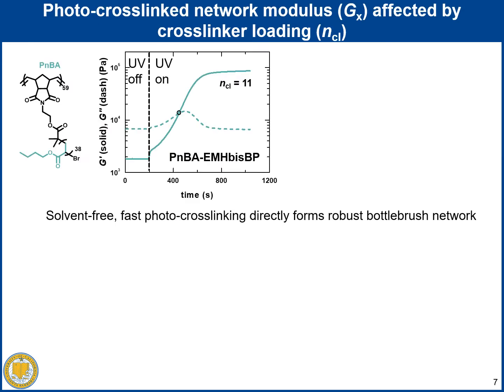Indeed, let's first take a look at a particular bottlebrush polymer with butyl acrylate as a sidechain and at a specific crosslinker loading, NCL equals 11. As shown, the UV light exposure resulted in an immediate rise of the storage modulus and loss modulus. After about 200 seconds, G' and G'' crossover, which represents the viscoelastic liquid to solid transition. As curing continues, G' and G'' eventually plateau, indicating the completion of crosslinking.